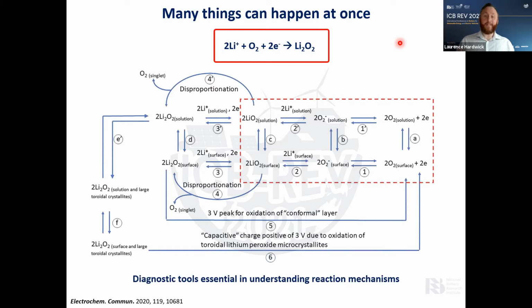Now, if we look at all the processes that can happen on the way of forming the lithium peroxide and also its oxidation back to oxygen, you can see that in reality, it's a much more complex set of processes, which really begin when oxygen is first reduced. It can either be adsorbed onto the surface or in solution, and so you can form the superoxide either on the surface or solution phase. And you can see all the different equilibria here taking place, and this all depends on the type of solvent and salt concentrations within the electrolyte, which guide these equilibria.